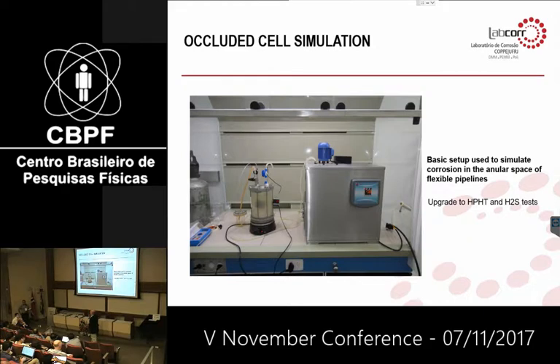Yeah, but how much hydrogen is in your material after the test? How do you analyze for that? In our lab, we used to control the aggressivity of the environment by the H2S concentration in the liquid phase. Okay. So it is within the range 5 to 25 ppm.